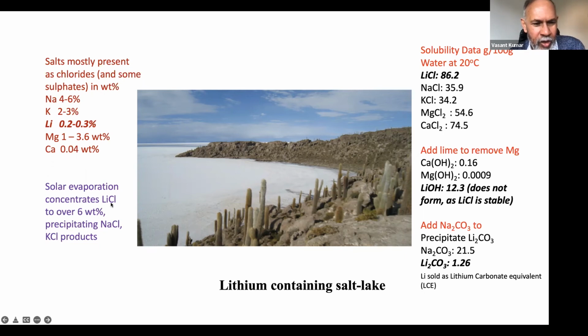They have been in use for ages for potassium, for example, for the fertilizer industry, except that lithium has a different solubility from potassium, so therefore it concentrates in the salt. By addition of lime, one can remove the magnesium, which can otherwise pose a problem, and then get the lithium as lithium carbonate by adding sodium carbonate. So there's a lot of transportation required to those high altitudes, with things going up and down, and all kinds of raw materials required, like sodium hydroxide and sodium carbonate.